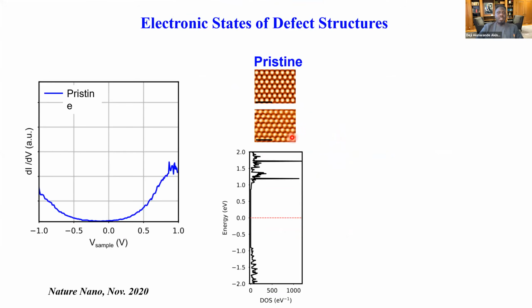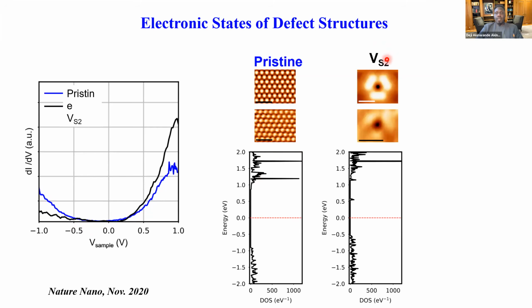So Seban did spectroscopy, and of course you can also do the STM in the same positions. He did spectroscopy, and I think this really concludes the mechanism. If you do spectroscopy, of course it's a semiconductor, so you have a region that doesn't conduct in a pristine material. DFT calculations show that for a single sulfur vacancy, the vacancy itself is not conductive - that's the black curve here. The vacancy does not conduct, and that agrees well with DFT calculations.